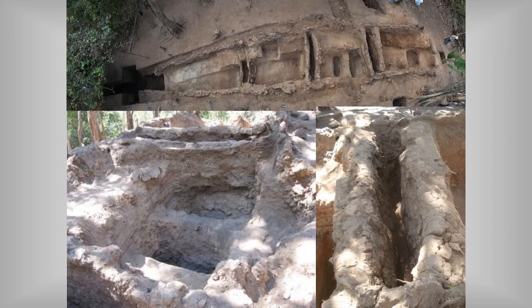The Chinese dragon kilns usually have secondary openings in the walls where you can add fuel. And this may be what inspired the Khmer, but they dug trenches through the ground, and we found a lot of charcoal in those trenches. So it seems to have been based on some secondary ideas of what the Chinese were doing, but not eyewitness observations. They figured out that you do need to make secondary firing areas for one very long kiln, but they dug trenches instead — so it was their own development.